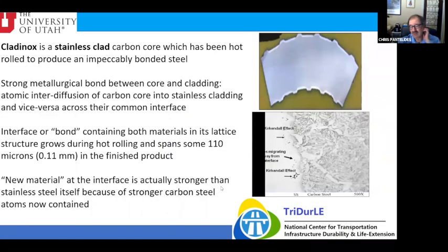So Cladinox is a stainless clad carbon core, which is hot rolled to produce a very good bonded steel. There's a good metallurgical bond between the core and the cladding because of atomic interdiffusion into the stainless cladding and vice versa. It's a common interface, as you see over here. And this bond has both materials in the lattice structure and grows during hot rolling and spans some 110 microns, or 0.11 millimeters, in the finished product. So this is some kind of a new material at the interface, which is actually stronger than stainless steel itself because of the stronger carbon steel atoms it now contains.